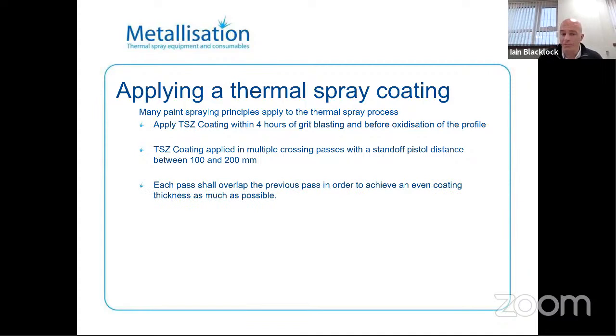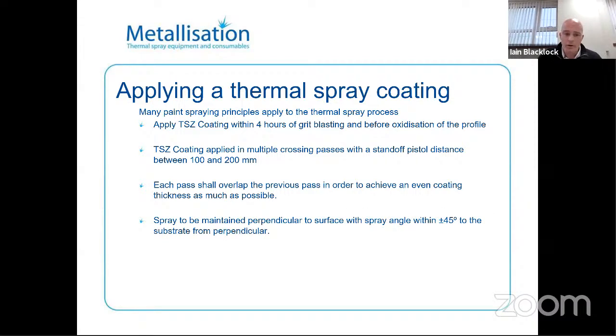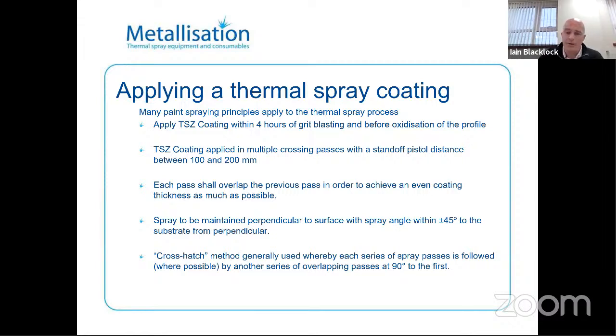Each pass overlaps the previous pass in order to achieve an even coating thickness as much as possible. You want to try to maintain perpendicular to the surface and no more than 45-degree angle of the pistol to the substrate. This gives the best coating properties. And typically crosshatch is used within the industry because it helps to give a nice even coating when you finalise a coating system. You apply the multiple passes and you continue to apply it until you've got the required thermal spray zinc coating thickness. Again, as soon as you've sprayed it, you can check this with PosiTest and Elcometer gauges.